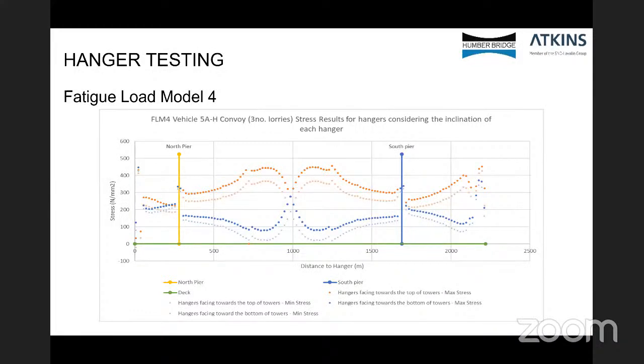Because we had concerns over the FLM3 modeling we've done, and particularly around the lambda factor we used, we did a further analysis of the bridge for fatigue load model 4. That is a much more complicated fatigue model than fatigue load model 3. It includes over 23 different vehicle designations, and it runs the different vehicles in different convoys across the bridge. Although it's quite analytically heavy, what that proved was that although the lambda factor was quite inaccurate for long span bridges, the stress range throughout the hangers was within what we previously specified. And what you can see on this graph is the difference between the dots is the fatigue range that we determined. Look to the next slide, please.